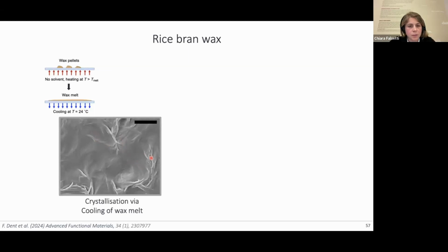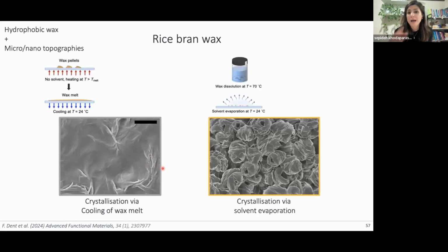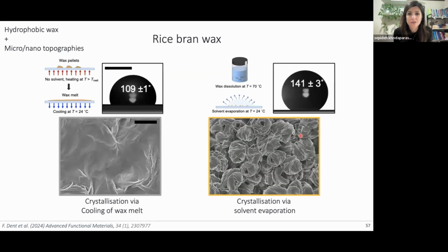If you melt and solidify, it's going to give you just a few wrinkles. But if you add solvent and solidify or crystallize by solvent evaporation, now you create these beautiful structures onto the surface. So you're looking at exactly the same chemistry, but just changing the crystallization path from cooling crystallization to evaporation induced crystallization. And obviously, because you're adding surface roughness, you're increasing the water contact angle on these surfaces.